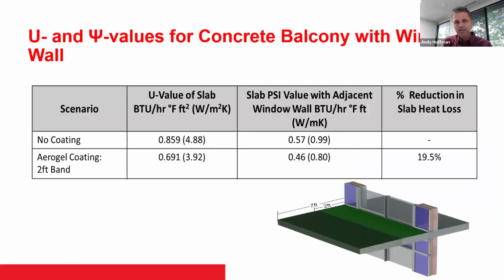So up until this point, we're talking about steel penetrations, whether it be roof penetrations or balcony penetrations, and controlling the condensation risk. We've also done a lot of third-party modeling with engineers looking at this on concrete. And when we put this on concrete, particularly balconies, now it becomes an energy savings play. In this picture at the bottom, we did a detail where we modeled coating the entire balcony slab, in this case 7 feet, or just coating out 2 feet and doing a 2-foot rubber band. So we're just coating the top, sides, and bottom of that balcony, coming out 2 feet from the window wall or curb, whatever the design may be, and putting on 2 coats for 100 mils. Again, rubber band approach, top, sides, and bottom, 2 feet out from that window wall or curb design.